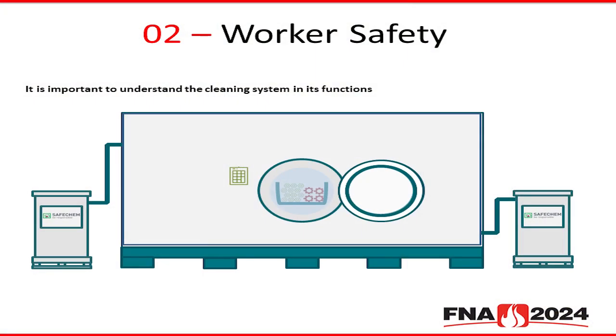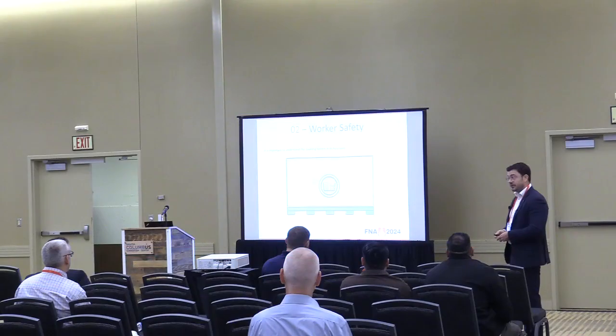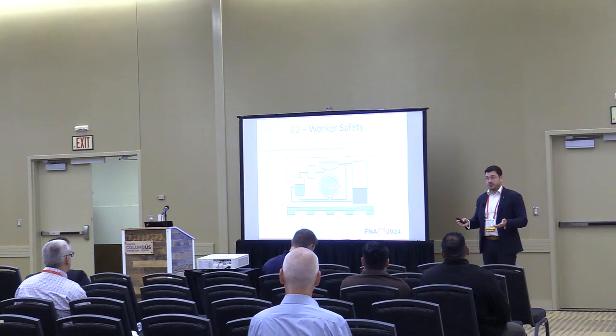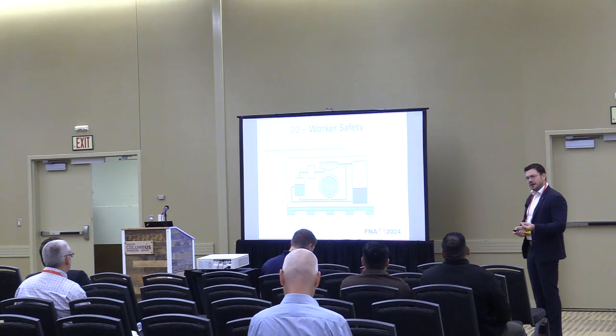And that system works differently to the old technology, where you don't bring the parts to the solvent, but actually you bring the solvent to the parts. You have a cleaning chamber, which is getting closed, and only at that moment you apply the different cleaning steps. With a first wash, some mechanics to also remove particles. You have filter systems included in the machine that will then filter out the particles. You may have a second wash for the rinsing part that, if needed, can also be done aqueous. You don't have to do it in two solvent steps, but depending on the contamination, you can also build in an aqueous-based cleaning tank. And then you normally still have a very little layer of oil left on the parts, because the cleaning quality is always only as good as the last tank has been contaminated, and you cannot always have it at 100% clean.